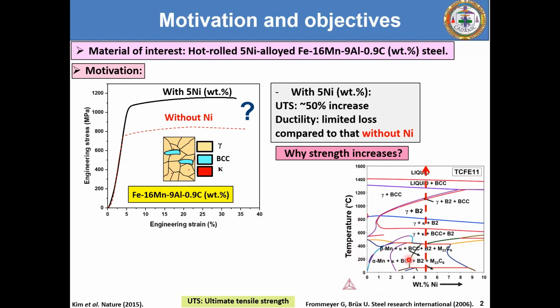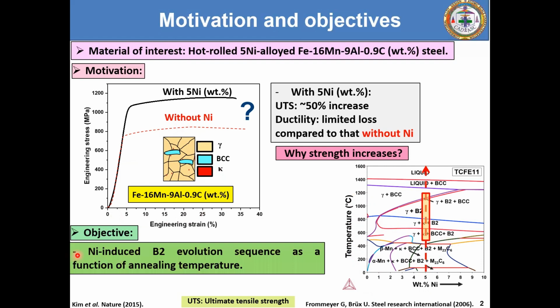So now this means that it is very interesting to investigate the evolution of the B2 phase in the microstructure. To this end, the objective of my research work that we have designed is to investigate the nickel-induced B2 phase evolution as a function of annealing temperature, where annealing was performed at a wide range of temperatures ranging between 500 to 1200 degrees Celsius.